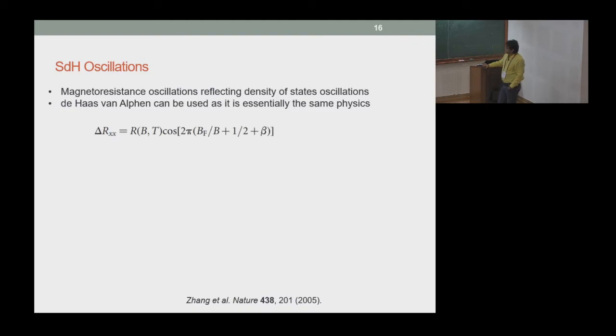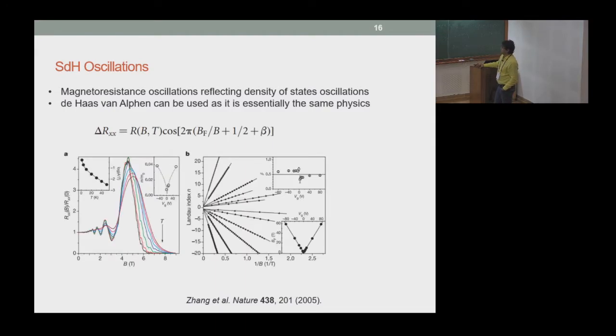This idea is of course used a lot in condensed matter, but in the 2D world, it was powerfully demonstrated by the first experiments on graphene, which is just a simple Dirac band. You measure these quantum oscillations, which have terms that relate to the area of the Fermi surface, and this phase, which can be extracted from the slope of this plot.